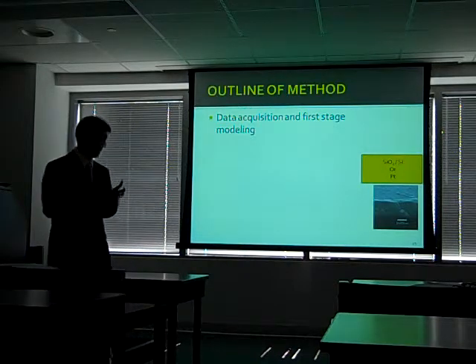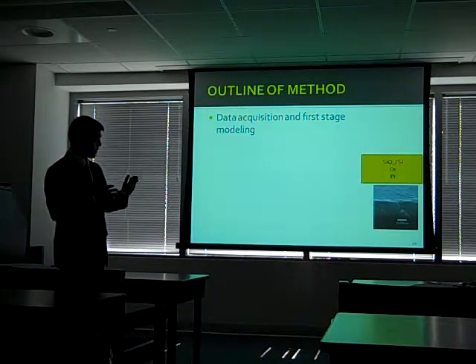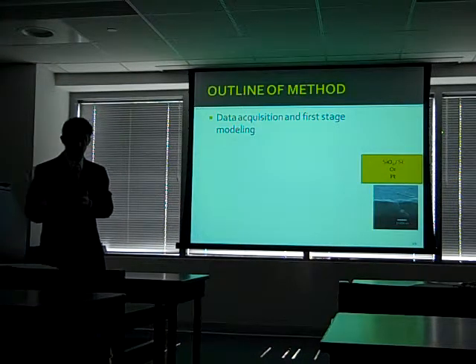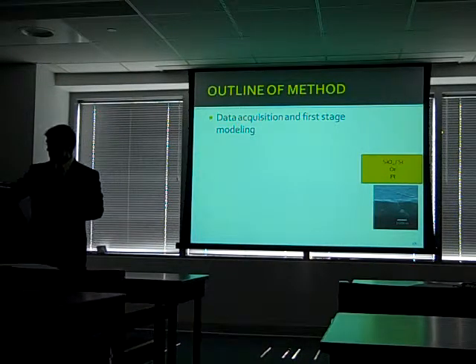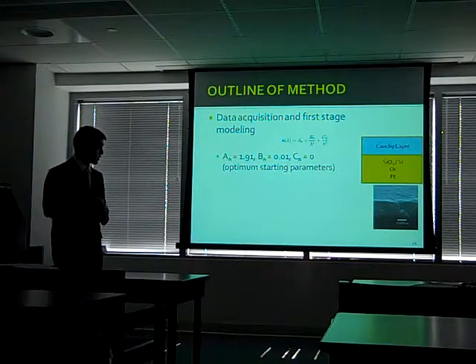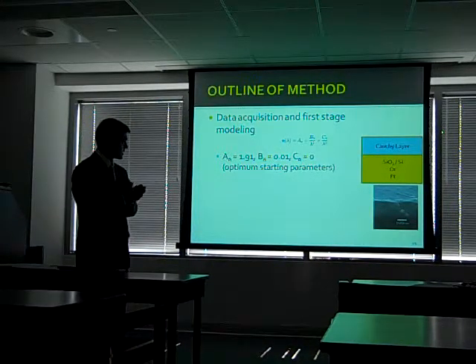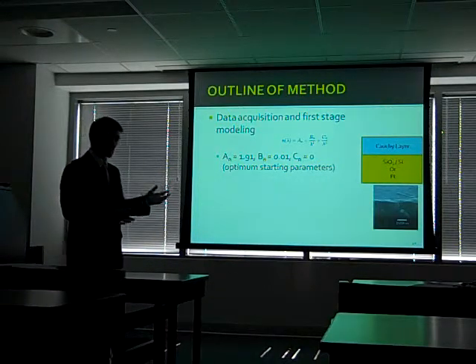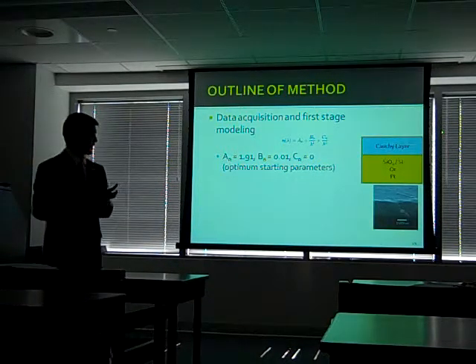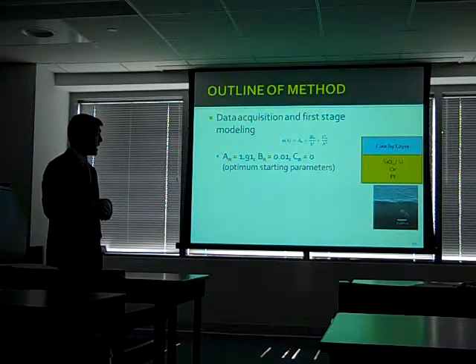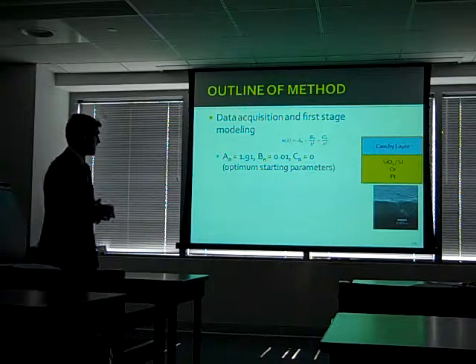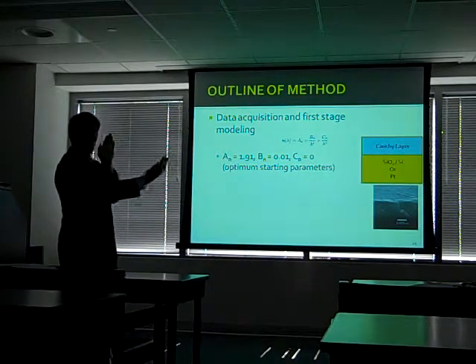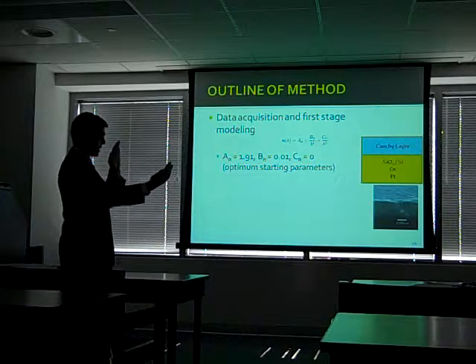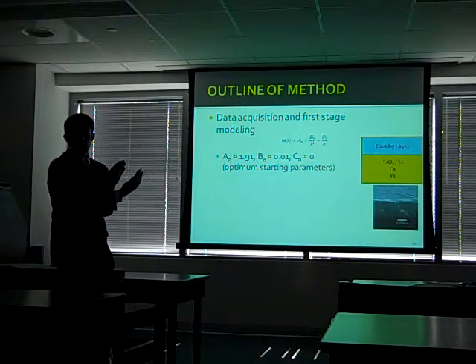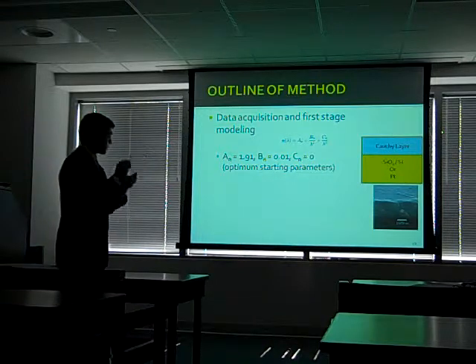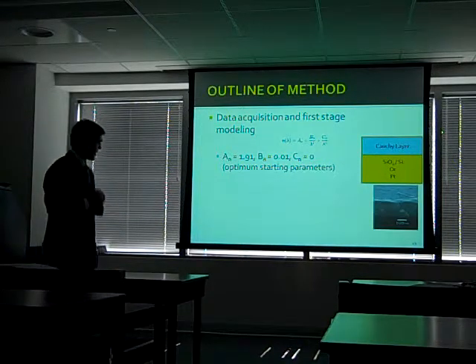Data acquisition is the first step. So we acquire the data with the VASE, and then we'll start to build our model. Depending on the substrate, is it platinum or is it on silicon? And then on top of the substrate, we'll put a Cauchy layer. A Cauchy layer is simply another parametrization like the Lorentz oscillator. But it's a phenomenological model that fits the index of refraction well in the transparent region of the spectrum. So for this, my data set is from 250 nanometers to 1,000 nanometers, and I've restricted the range to 600 to 1,000 because that's where the material is transparent, and fitting then the index of refraction.